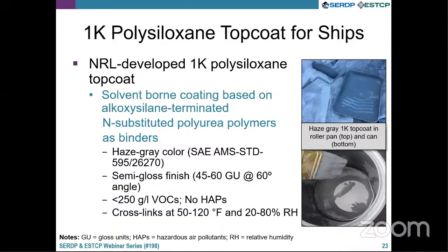Our formulations were less than 250 gram per liter VOCs with no HAPs, no isocyanates or other hazardous materials. And we developed the formulation so that it will sufficiently cross-link over a wide range of conditions, about 50 degrees to 120 degrees Fahrenheit and 20 to 80% relative humidity.